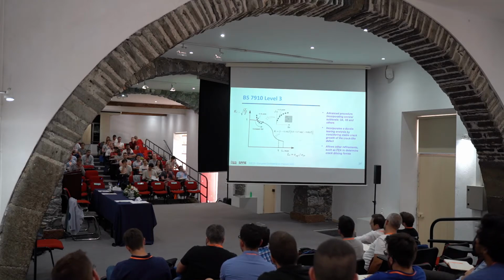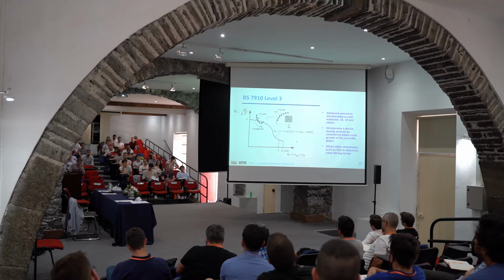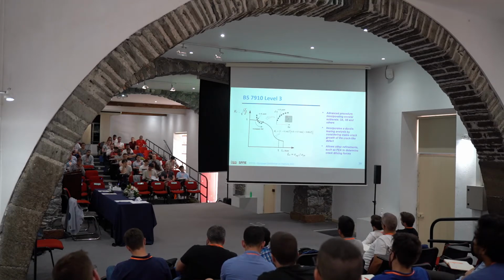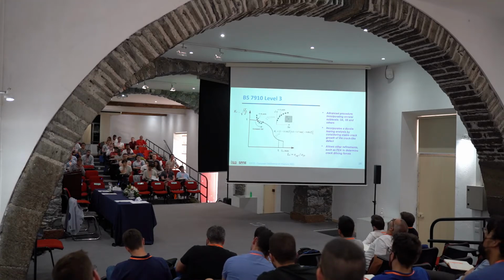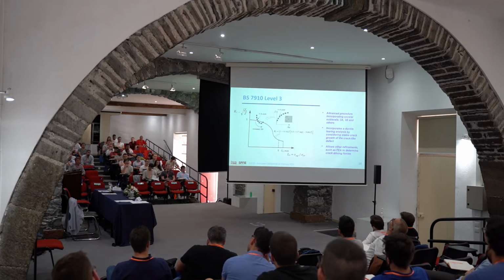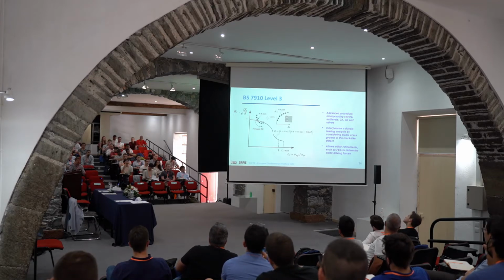Again, the procedure has many details, but you have just to follow the procedure. But it's essentially like this. You need a resistance curve, an R curve, J resistance curve, and as the crack is increasing, your assessment point is also moving. Okay, and then you do your assessment depending on your expected ductile tear.